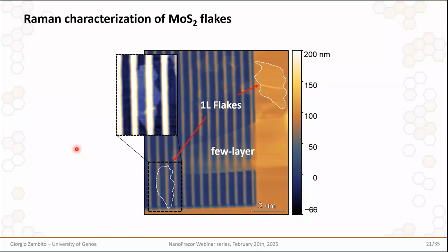So in this image, it's shown the result of this exfoliation process. And here you can see the presence of two monolayer flakes of MoS2 that are indicated by this white dashed line, along with a thicker few-layer flake in the central area. The first interesting thing is that we notice a high degree of conformality between the monolayer flake and the underlying pattern, to the point that it is almost impossible to locate it by eye. And that is because, of course, we are talking about a material less than 1 nanometer thick that is lying conformally on top of a nanopattern that is around 60 nanometers high. It is slightly more visible if we exaggerate the z-axis scale, and here we can barely recognize the shape of the monolayer flake.